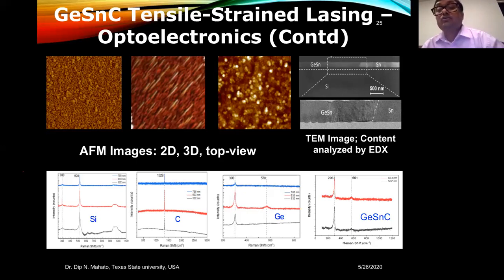And then you can see the TEM, transmission electron microscopy image also, that can tell you the silicon and then germanium tin on top of the silicon layers. So that is the cross-section view. It's not the top view. When you do the TEM, that is another technical thing that you have to be expert on. You have to cut in a certain direction so you can get the cross-section view of the image like that.